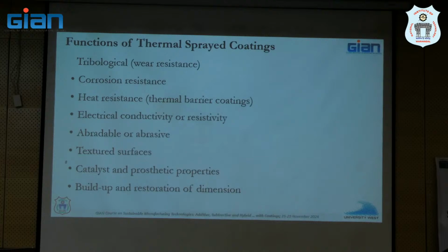So same as what we spoke yesterday, if I pick the right material, I can achieve any function from thermal spray, right? I can get corrosion resistance. In the simplest case, people spray bridges now in the US with thermal spray, only doing aluminum or aluminum zinc, right? So you can get corrosion resistance. You can get very aggressive corrosion resistance in a land-based gas turbine where you won't use aluminum or zinc, you'll use something far more complicated, correct? But you can get corrosion resistance.